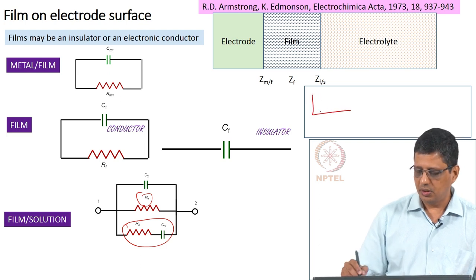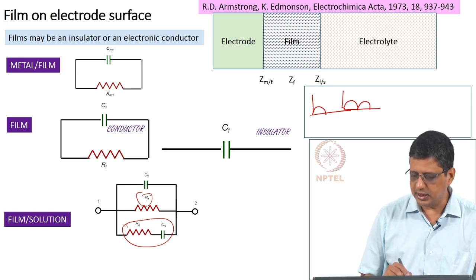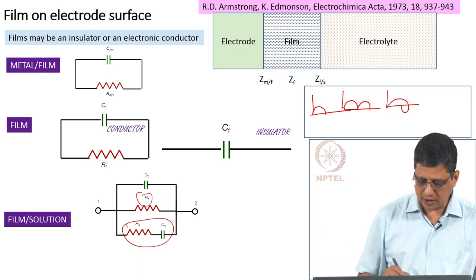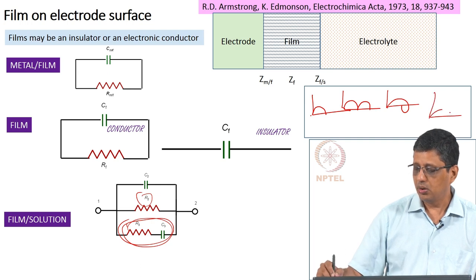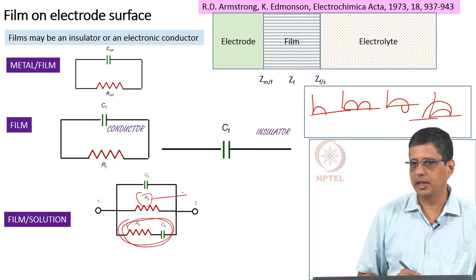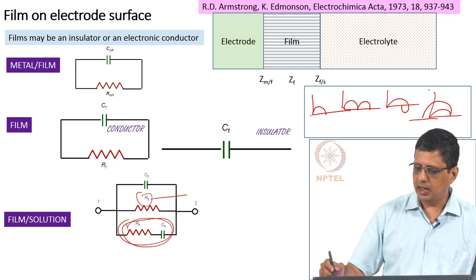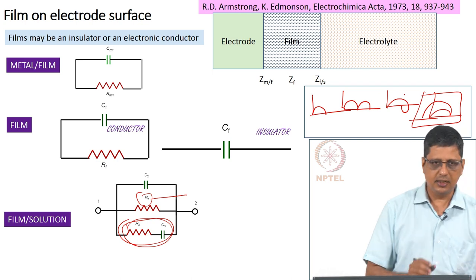That means you can get only this if you have only R2 along with C2. You can get this type of behavior assuming all these elements have positive value. You can get this type of behavior assuming R3, C3 are allowed to have negative value. You can have this type of behavior if you assume that R2 can have negative value. And of course, when you have a situation where you have passivation, the last one is likely to happen. But these are simplified versions,